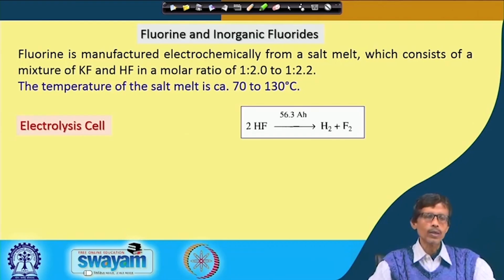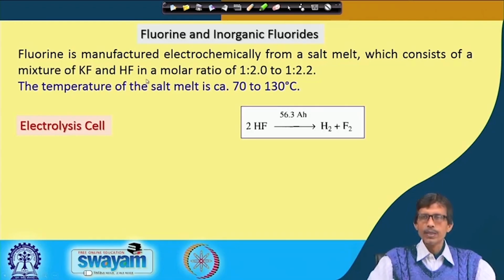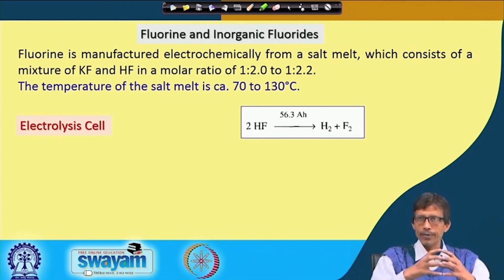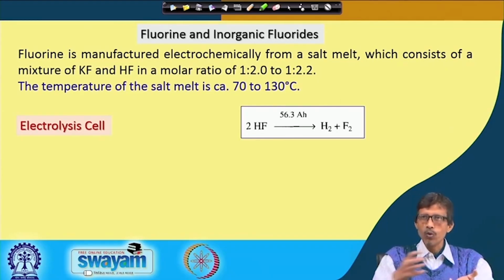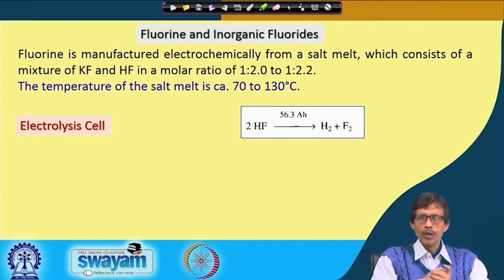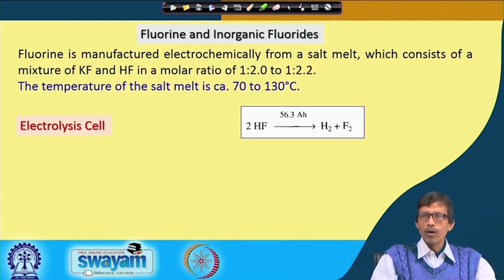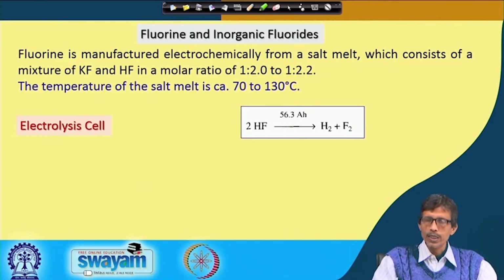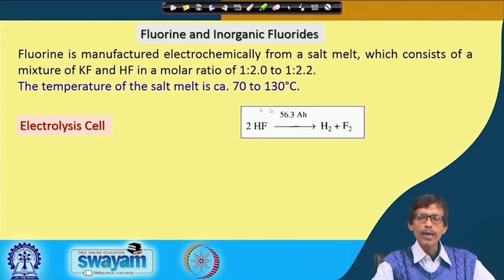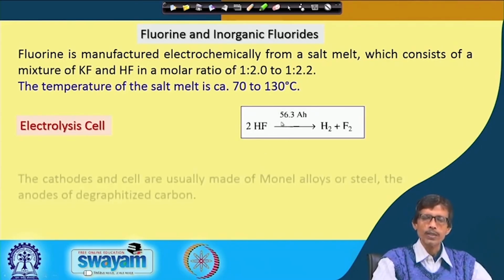So, if you have the melt, as I told above, a melt of KF and HF, it is giving you potassium bifluoride as well as your salt of HF. But if you go for the electrolysis of that melt, the potential is set in such a fashion that only the oxidation of fluoride ion and the reduction of the hydrogen ion occur. If you consider HF, from its electronegativity difference, H will remain as H plus in the melt medium, and F will remain as F minus. So, the fluoride ion will undergo oxidation, and H plus will accept those electrons from the fluorides, giving you the production of hydrogen. So, this particular procedure will be very useful not only for production of fluorine, but it can also produce hydrogen, if we have some mechanism to separate the hydrogen gas from the fluorine gas being produced. A rating of that particular electrolysis cell is also given, which is 56.3 ampere hour.